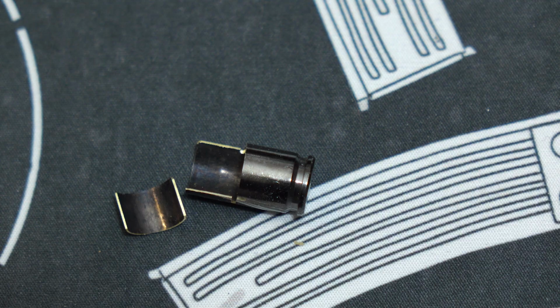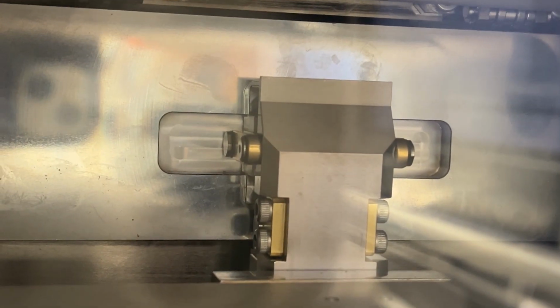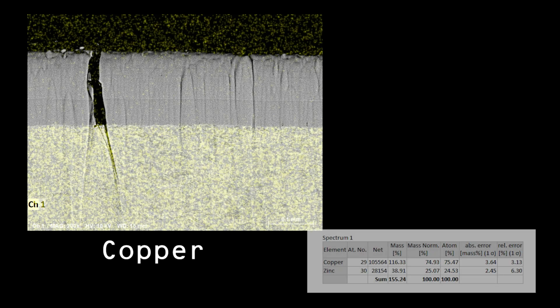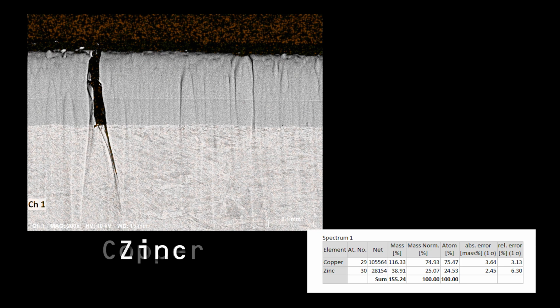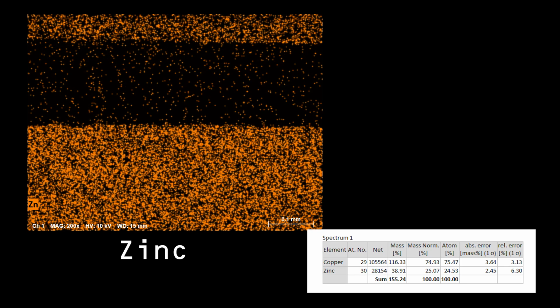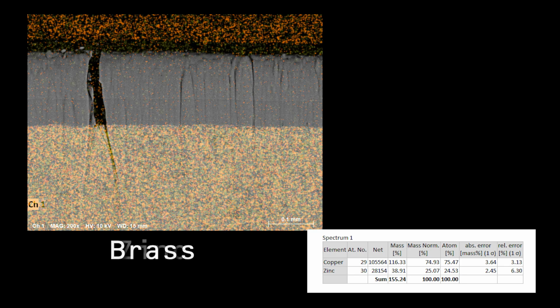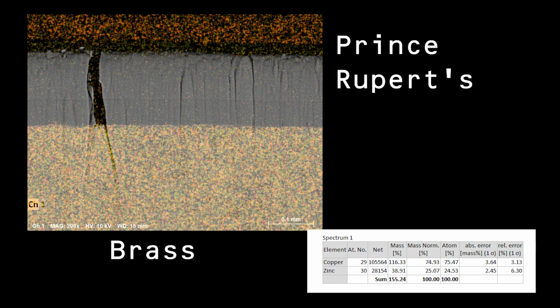So I also cut it up, did some ion milling, and here's what we got. Now, most cases are made out of something called cartridge brass, which is about 70% copper and 30% zinc. There's some leeway in there, but that's generally what we're working with. In this case, we've got 75% copper and 25% zinc. That change in composition moves it from cartridge brass to an alloy called Prince Rupert's metal.